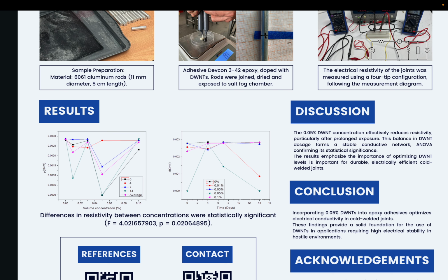these joints. These findings suggest that there is a delicate balance in the concentrations of double-walled carbon nanotubes needed to optimize the electrical conductivity of the epoxy adhesive. At lower concentrations, such as 0.01%, the reduction was less significant, indicating that the quantity of nanotubes was insufficient to form an effective conductive network through the adhesive matrix.